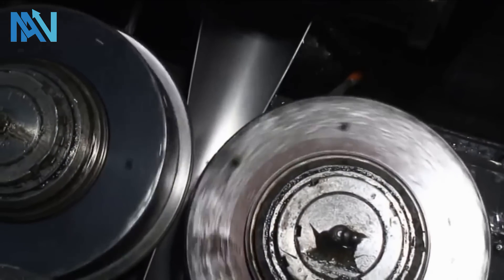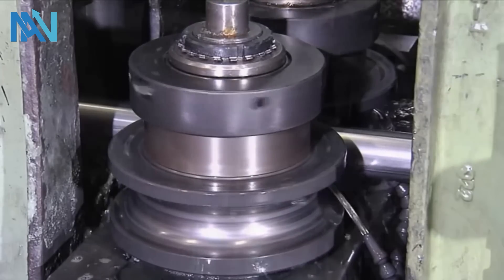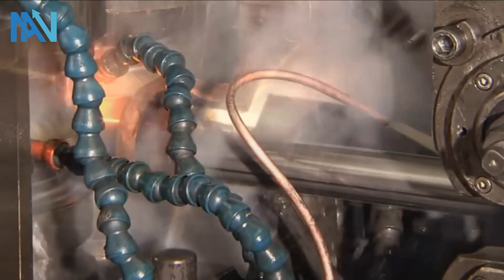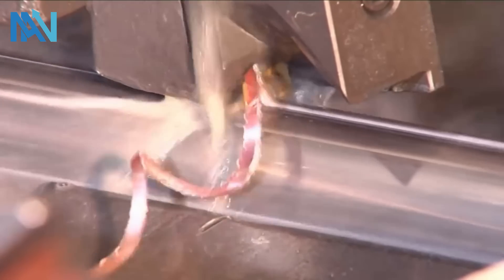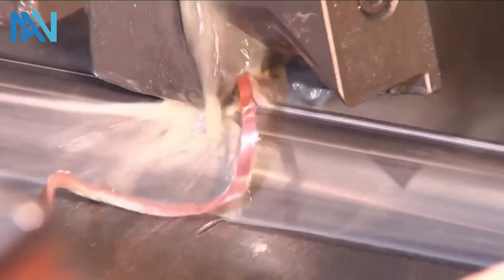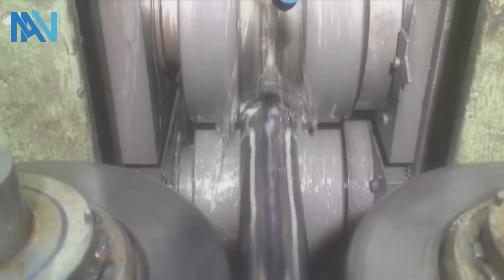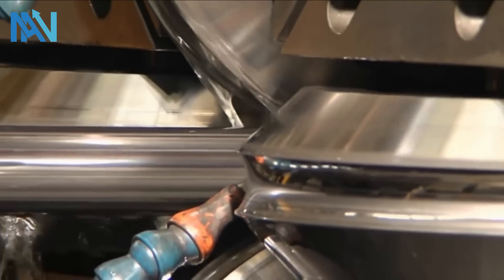Our welding facilities produce tubes with external diameters of up to 114 millimetres and wall thicknesses of up to 8 millimetres. Characteristics of the tube seam are measured using ultrasonic testing. The welded tube is passed through calibration rolls and then cropped to the desired length.